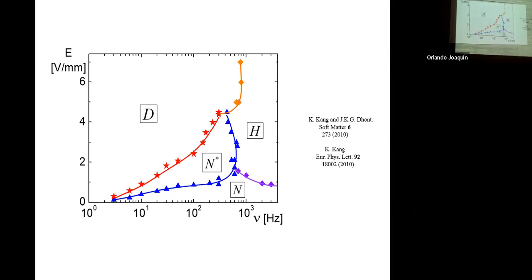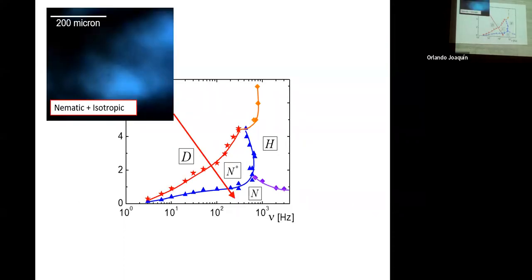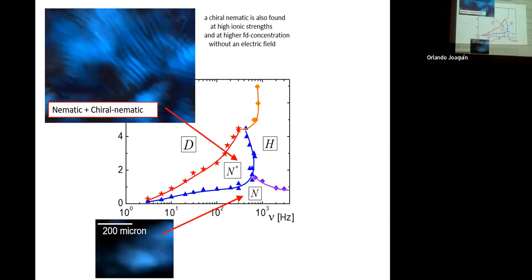But if you apply an electric field, you will induce different phases. So let me explain which phases those are. As I said, this is the normal situation without the field, called the N for nematic, but in equilibrium with isotropic. And then if you increase, below this frequency, you increase the field strength, you also get a cholesteric nematic.